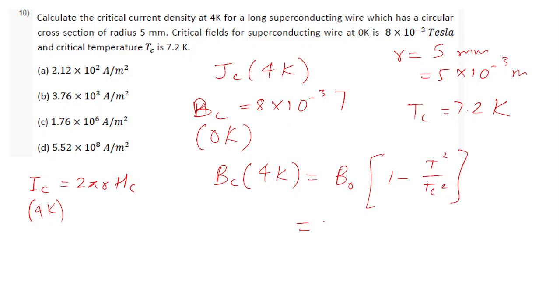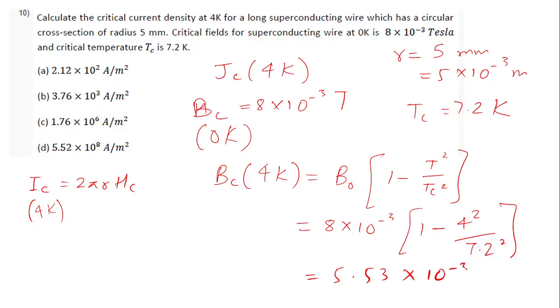This is the value at 0 Kelvin, 8 times 10 to the power minus 3, times 1 minus T square, where T, the temperature that we are interested in, is 4, squared. Tc is 7.2 Kelvin, so square of that. When we do this calculation, we'll get 5.53 times 10 to the power minus 3 Tesla. So we calculated this. Now to get HC, it will be BC divided by mu naught. And then we'll put that here.